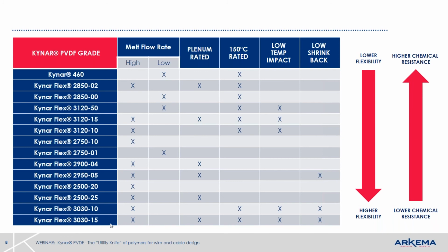Kynar 3030, that's a very high melt flow rate material. It's plenum rated to 150 C, has low temperature impact, has very low shrinkage. So this is favored by fiber designers, the 3030 type cables. Conversely, the Kynar 460 PVDF melt flow rate is very low. It's rated to 150 C. So if you see this list of different grades, you'll notice that the flexibility goes from very low to very high. So depending on your requirement, you could choose a grade for flexibility.